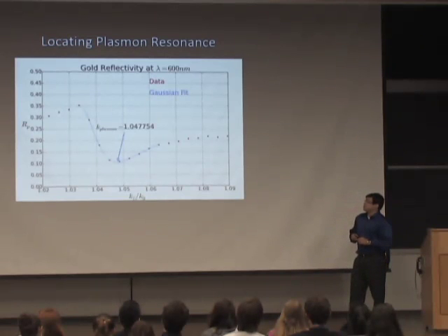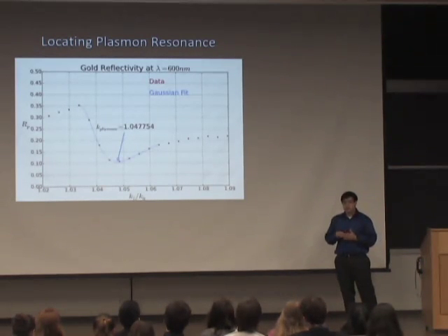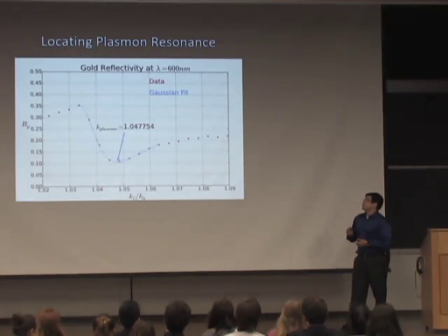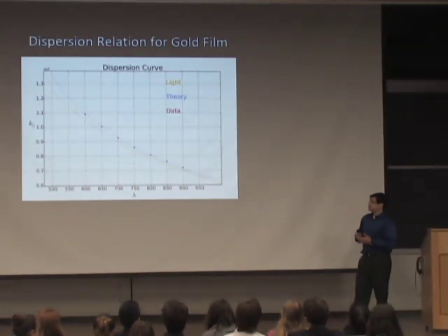So what we do is fit this data with a modified Gaussian to pinpoint the minimum of where the plasmon resonance would be, and then taking that plasmon resonance location for different wavelengths allows us to generate a dispersion relation for this plasmon.